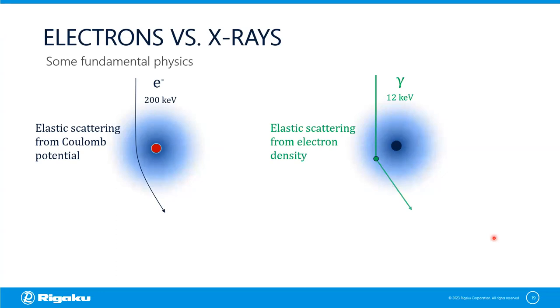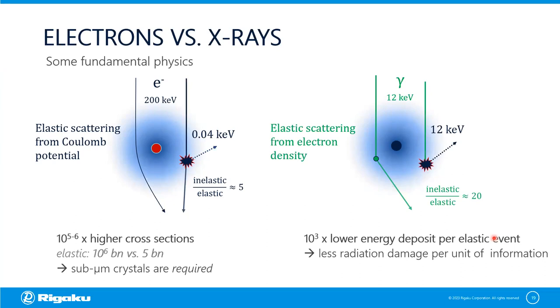So what's the difference between electrons and X-rays? Fundamentally, electrons are scattered by the Coulomb potential. X-rays are scattered by the electron density. This results in electrons having a 100,000 to 1,000,000 times greater cross-section, and it means that sub-micron crystals are required. Crystals larger than a micron will essentially stop the electron beam. It also has implications in that we often see dynamical diffraction, multiple scattering events, with electrons where we would not see them with X-rays. With X-rays, we deposit much lower energy per event, with the implication that we have much less damage. So electron diffraction experiments take seconds to a minute or two. X-ray experiments may take a minute to several tens of minutes.